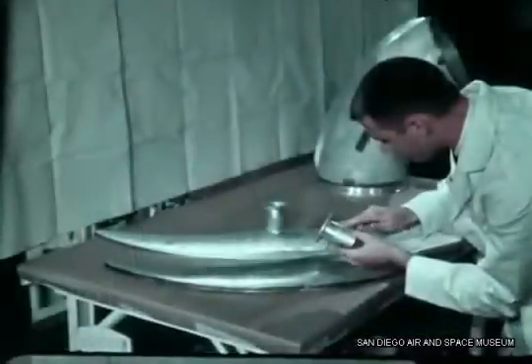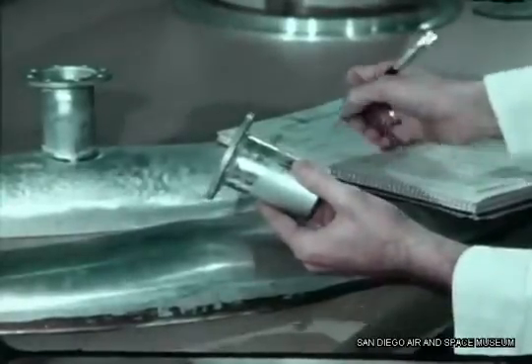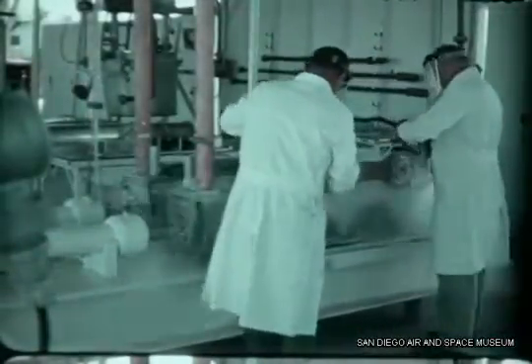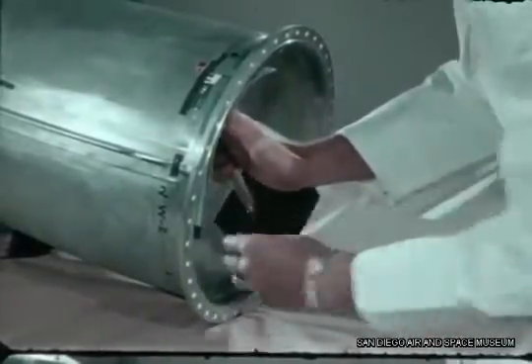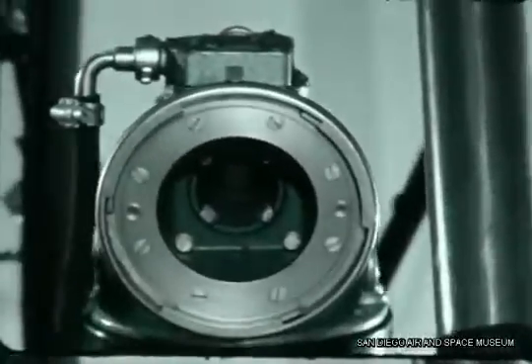Production inspection methods were applied to the test program to maintain quality control. The welds were inspected using destructive and non-destructive testing. Coupons of sample metal from the same weld schedule were tensile tested to evaluate the material's mechanical properties. Tests were made at both ambient and cryogenic temperatures. Inspection with dye penetrant revealed any surface flaws, while x-ray inspection of every weld area showed the internal quality of the weld. The 100% x-ray inspection technique helped keep quality high, with more than 90% of all welds made meeting Class 1 requirements. The use of x-ray inspection and micro-photography also helped in developing manual welding techniques for sump welding.